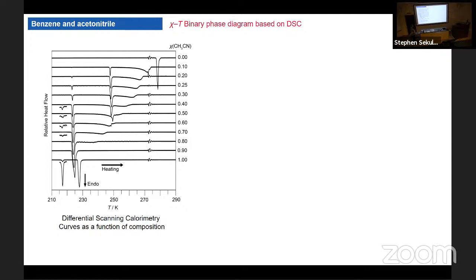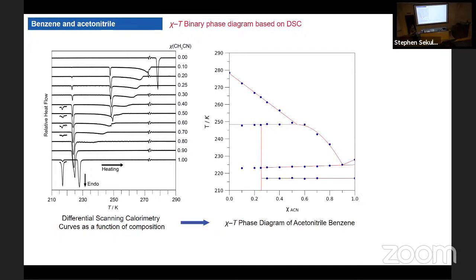and benzene. What we have here, we have prepared a couple of mixtures, and Christina did this here in our lab. We have mixtures starting from pure benzene up to pure acetonitrile and all of those combinations. As you can see here, we have different endothermic peak maxima, minima in this case, that are shifting. And as they are shifting, they are outlining the phase diagram of acetonitrile and benzene. Looking at these peak minima, we can plot the phase diagram. And this is the solid-liquid phase diagram of acetonitrile and benzene that is being created in our lab. And here below, of course, would be the region that we as chemists would be interested in for Titan.